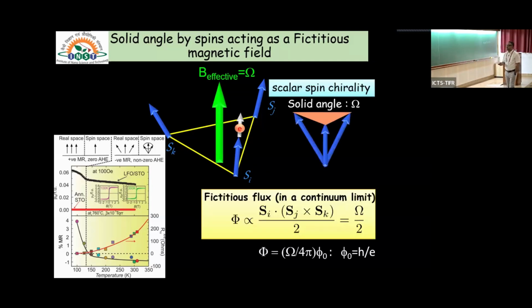So what was the idea? The idea was this phase is proportional to the solid angle subtended by these 3 spins. So what we thought is that at low temperature, the spins are parallel to each other, they are locked. But when you increase the temperature, because of the thermal fluctuation, the thermally stable state is a spin canted state. And because of this spin canting, this system is gaining some Berry phase, and that is giving rise to this negative magnetoresistance or anomalous Hall effect. But the referee didn't like it. We are also not sure.